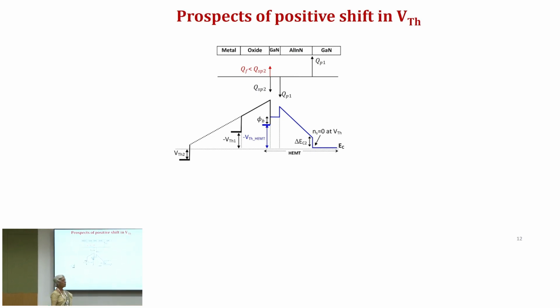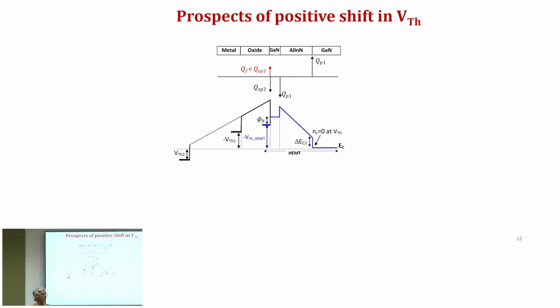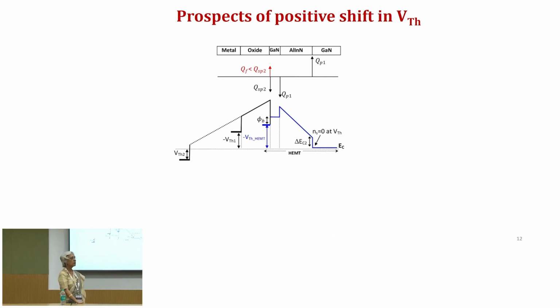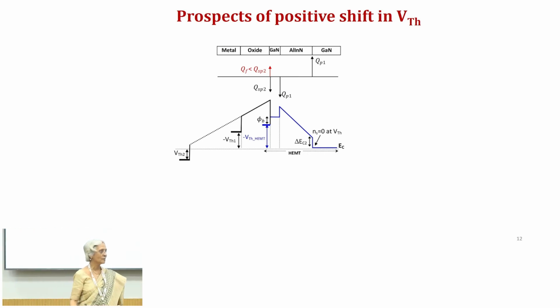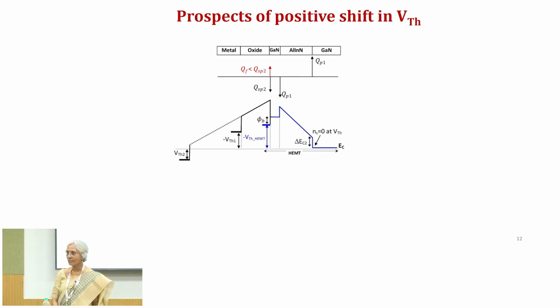And if we can make that oxide thicker, then of course, as you can see here, look at the electric field distribution in the oxide. This is how the energy band is going to bend, and then we are actually going to have a change of sign in the threshold voltage, and if you can use a thicker oxide, then the threshold voltage can actually be positive. This was a hypothesis, right? I will show you that this hypothesis was not 100% correct, but at least here it looks as if we can make the oxide thicker, then it is possible to achieve a positive threshold voltage, provided the charge in the oxide or charge at the oxide semiconductor interface is all negative charges.